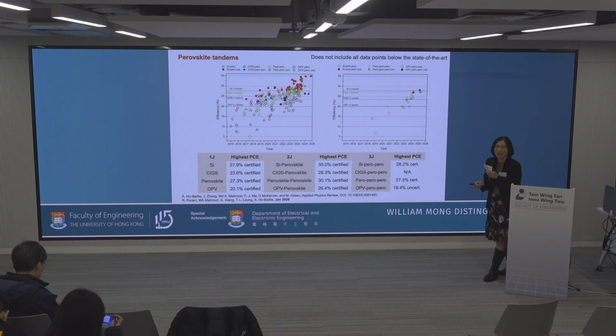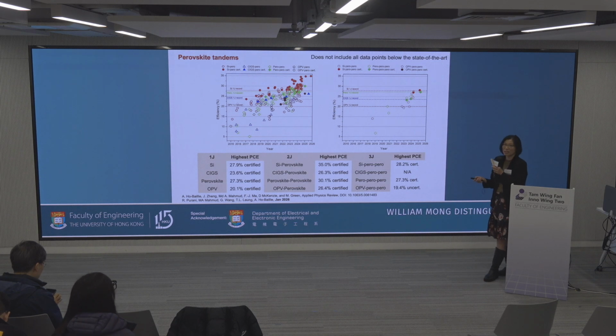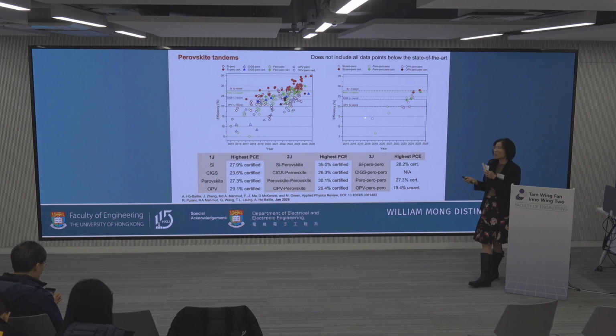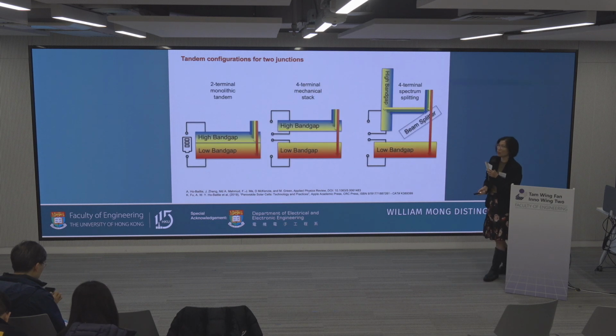But as you can see, when you add another junction, you basically add another 5 layers. Because you've got the hole selective layer, the electron selective layer, and then the positive electrode and negative electrode, that's 4 layers, and then you have the absorber, 5 layers. So for triple junction, essentially you've got 15 layers that you have to worry about, and therefore it's not as easy as the double junction. But it's got the efficiency potential.